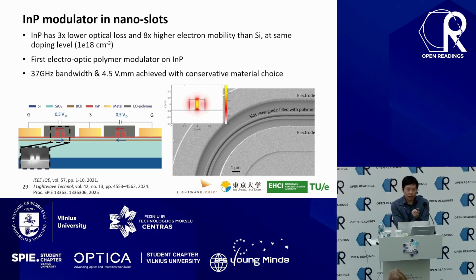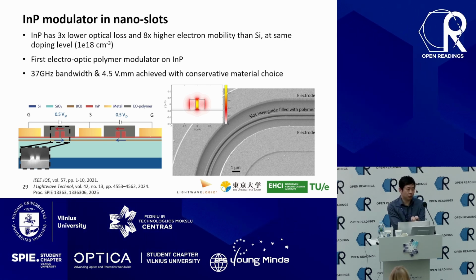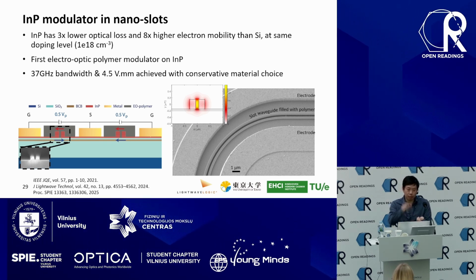And you can utilize this to create a very efficient optical modulator, because in the gap of this slot, you can fill in efficient electro-optical polymers. Then by applying an electrical field, you can modulate the polymer, which has a very strong interaction with the optical mode.